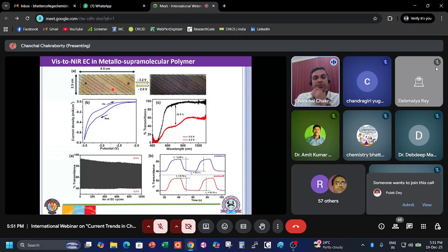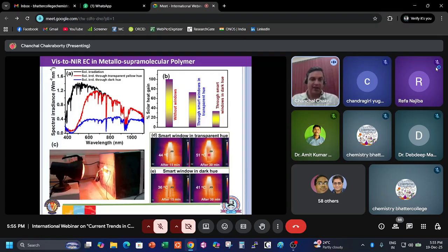Not only that, we checked with a transparent glass window, and after 30 minutes of continuous IR irradiation, it goes to 51 degrees. So it's a huge 51 degrees. Sunlight has only about 50% IR, so the room temperature is not increased that much. But in our summer, it can go to 50 degrees in certain cities. So it can effectively reduce that, but it cannot cut down the full solar irradiance.